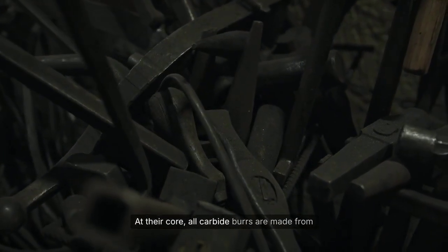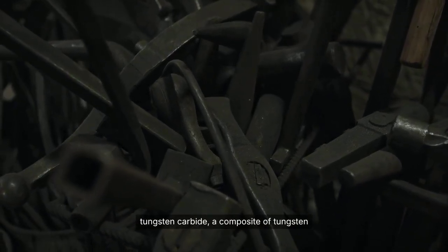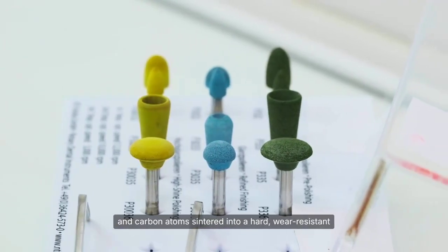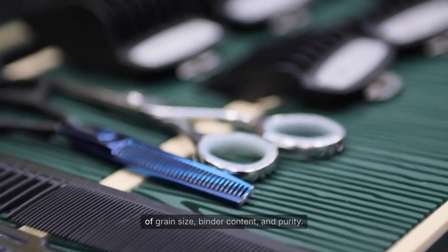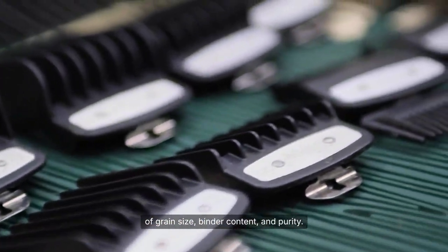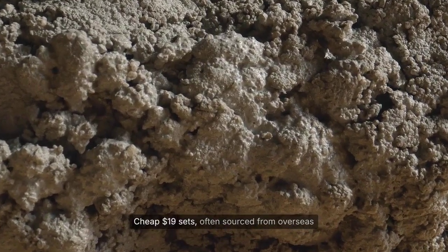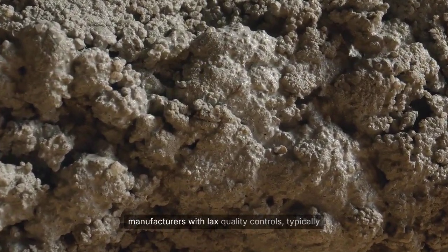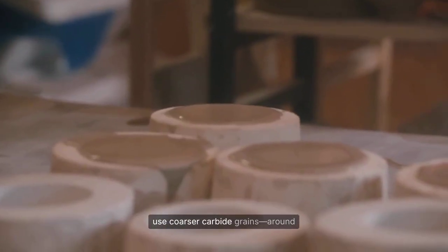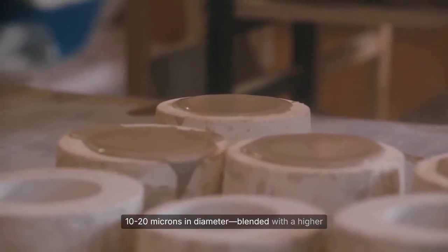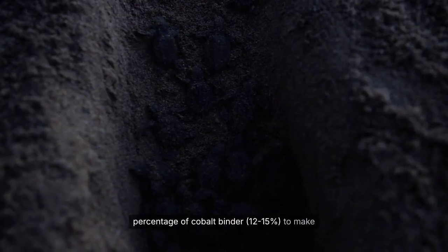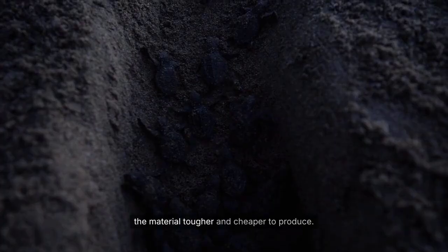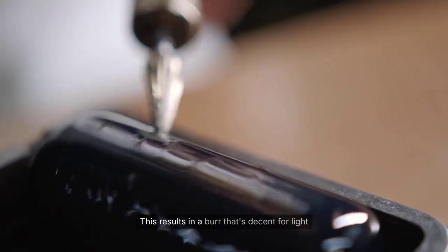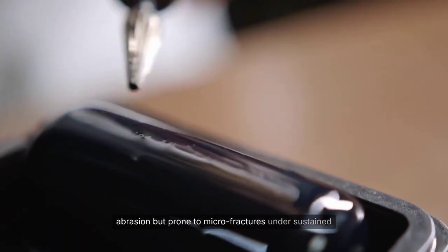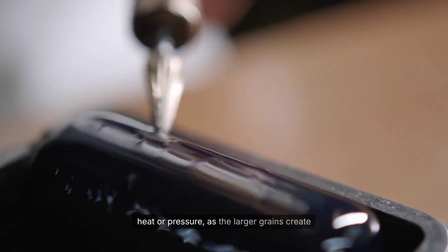At their core, all carbide burrs are made from tungsten carbide, a composite of tungsten and carbon atoms sintered into a hard, wear-resistant matrix. But the devil is in the details of grain size, binder content, and purity. Cheap $19 sets, often sourced from overseas manufacturers with lax quality controls, typically use coarser carbide grains, around 10 to 20 microns in diameter, blended with a higher percentage of cobalt binder, 12 to 15%, to make the material tougher and cheaper to produce. This results in a burr that's decent for light abrasion, but prone to microfractures under sustained heat or pressure, as the larger grains create weak points where cracks propagate easily.